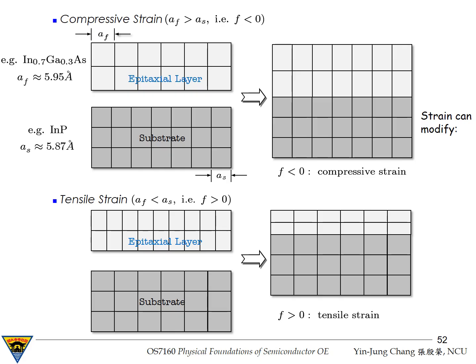So let's first consider compressive strain. Compressive strain occurs when the natural lattice constant of the film is larger than the lattice constant of the substrate. So we have A sub f larger than A sub s. The corresponding mismatch parameter f must be negative, because the film naturally prefers a larger atomic spacing, but must match the smaller substrate spacing at the interface. The film lattice is compressed in the plane of the interface, as can be seen in the diagram here.